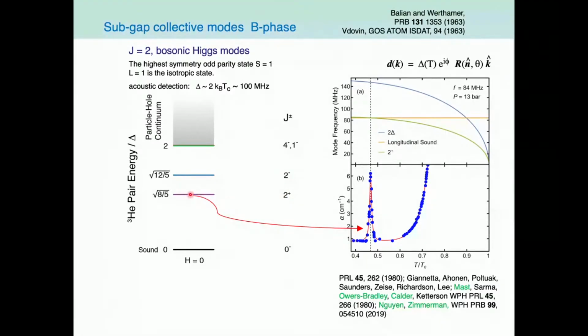The square root of 8/5 state is a subgap state that involves the real parts of the 18 component order parameter of superfluid helium-3. The square root of 12/5 involves the imaginary parts. For that reason, this one down here, the 8/5, is called the real squashing mode, and this one up here is called the imaginary squashing mode. The discovery of this lower one shows up at appropriate frequencies and temperatures as a really narrow spike. So there's going to be some spectroscopy that's relevant here.